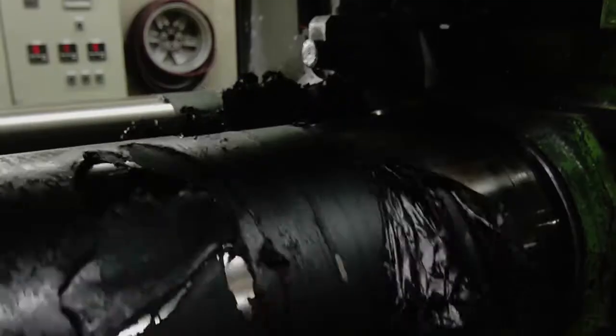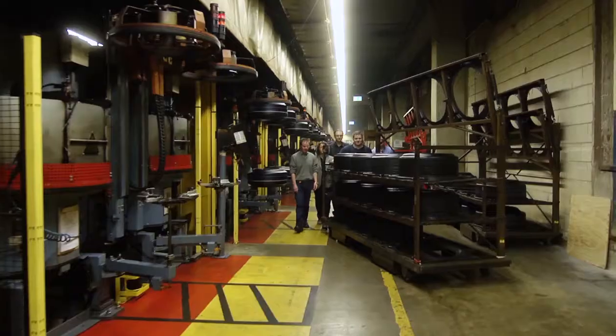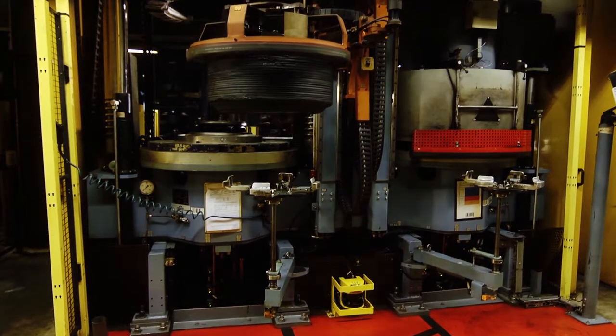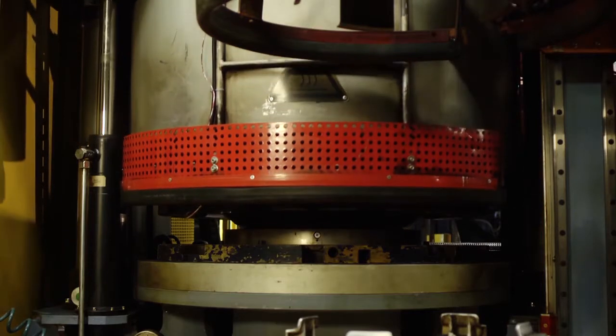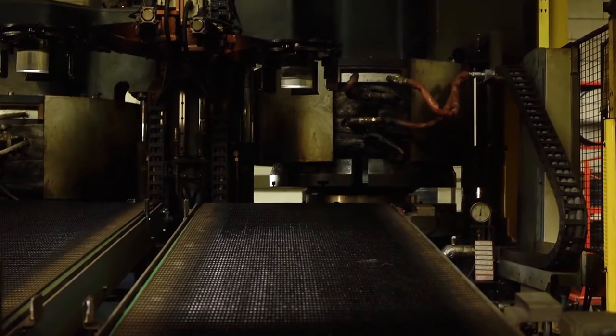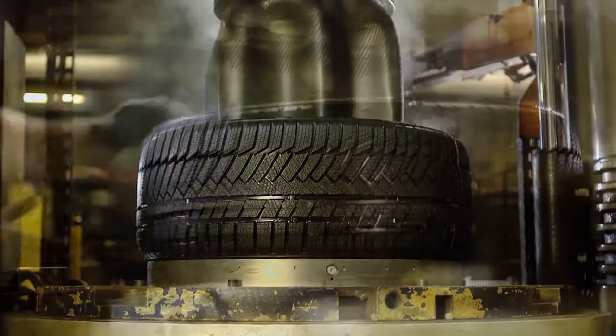The compound contains elements such as natural rubber, silica, carbon black, rapeseed and mineral oil, zinc oxide, sulfur, stearic acid, activation agents, antioxidants, and UV inhibitor. The green tire is then cured at the Aachen plant, where it is vulcanized in a mold at approximately 392 degrees Fahrenheit. The rubber compounds melt into vulcanized rubber and are inextricably linked together; after about 10 minutes of high pressure, the tire takes its final shape and tread.